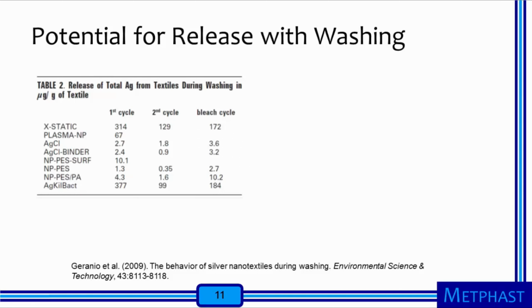Other authors have investigated the potential for releases of nanosilver from test fabrics during washing. Geranio and co-authors measured the release of silver from fabric containing nanosilver in a washing machine using a standardized test protocol. The table shows that substantial releases of nanosilver can occur and that the amount released decreases during a second washing cycle. Not surprisingly, the largest releases on an absolute basis were for fabrics that contain more silver to begin with.